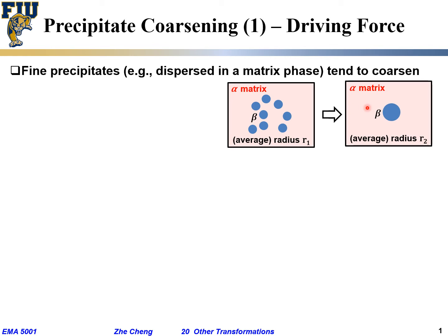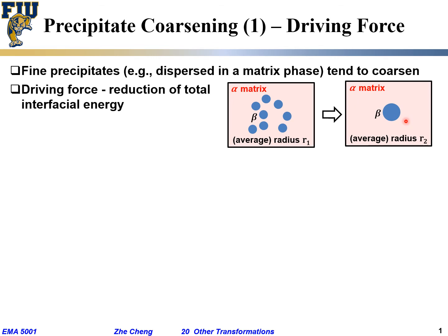For aerospace-grade aluminum alloys, if you anneal them at just two or three hundred degrees Celsius, even though they are strong initially, they will become as soft as food-wrap aluminum—very easily scratched or bent. This places a firm limit on processing temperature and application temperature. Nobody uses strong aluminum for high-temperature applications because around 400°C aluminum becomes very soft and cannot sustain significant mechanical load.